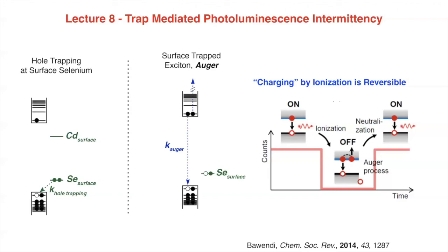Graded alloys can influence the probability of that Auger recombination and change whether or not that state undergoes luminescence. But in any case, this sort of charge transfer into the particle from a surface state leads to a metastable species that then does Auger recombination, and that Auger recombination competes with the photoluminescence. It becomes a non-radiative mechanism for recombination that erodes quantum yield.